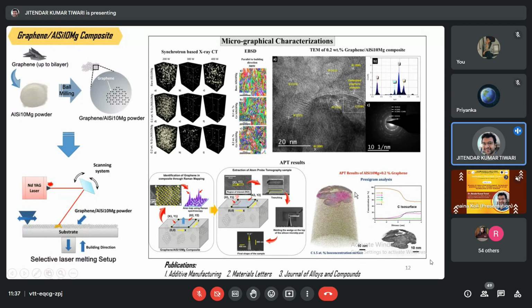And you can see here, this particular platelet is representing the embedded graphene inside the matrix. So this pink color is actually representing the silicon, and the gray color is representing the aluminum atoms. So basically what happened, this is the tip. We form this kind of tip, and we place it into the sample holder.